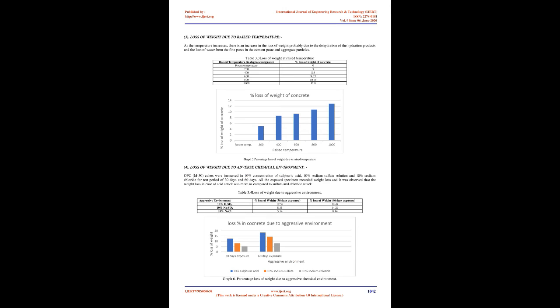Coconut fiber concrete was heated in an electric furnace at a heating rate of 10 degrees C/min to target temperatures of 200 degrees Celsius, 400, 600, 800, and 1000 degrees C respectively. At each target temperature, the specimens were maintained for 2 hours, monitored by a type K thermocouple. After each exposure cycle, the specimens were allowed to cool at room temperature for 24 hours and then tested to assess the residual strength and weight loss.